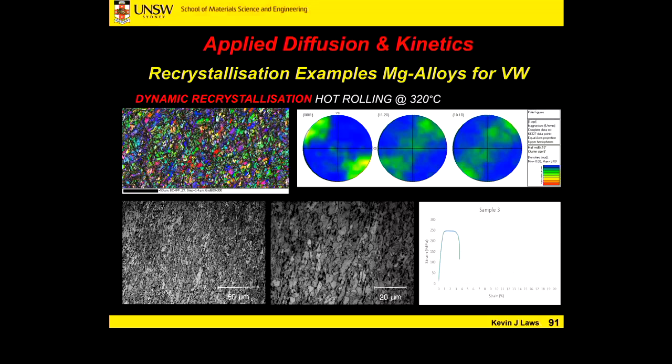Magnesium is a fairly brittle material. You have to get it to elevated temperatures at fairly low reduction rates to do the hot rolling process, but again, very close to the activation energy when atoms become mobile enough for the material to be very ductile. It's going to be very, very close to that recrystallization temperature.